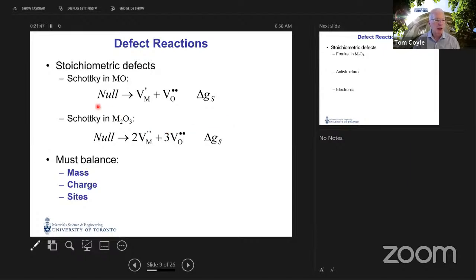So in this case, for this oxide consisting of a +2 cation and -2 oxygen, we have started from the perfect lattice and then created a vacancy on the cation site and a vacancy on the oxygen site. So we have one cation site, one oxygen site. So sites are balanced.